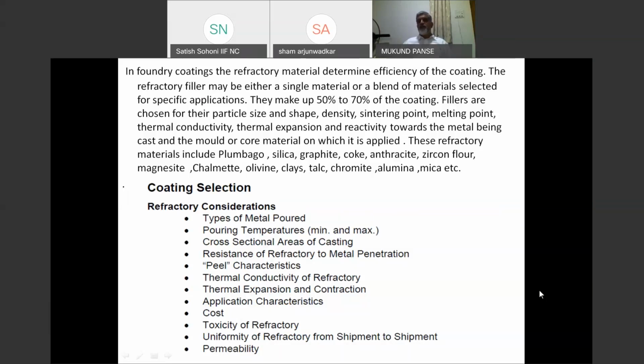See, the application may depend on the metal you are pouring and the size of the casting, the surface finish requirement, etc. The different refractory materials used are plumbago, silica, graphite, coke, anthracite, zircon, magnesite, olivine, clays, chromite, alumina, mica, etc. The refractory choice considers the type of the metal poured, pouring temperature, the thickness of the casting. The heavier casting will need better refractoriness because the sand is going to be heated for a longer time. Peel characteristic: the coat should not peel off. It should remain stuck on the sand or core.